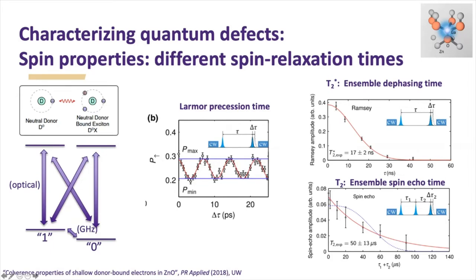The reason why in this ensemble measurement of many, many donors that this is decaying quickly is that they're all seeing different microscopic environments. We can actually rephase the spins, doing something called a spin echo by adding a third pulse. And when we do this, we see that now our quantum memory time is 50 microseconds. So we went from tens of picoseconds to tens of nanoseconds to tens of microseconds. And then we also want to know, well, in this material, we're pretty sure we know what's limiting this. It's due to zinc spins that we're not controlling for, that have nuclear moments.